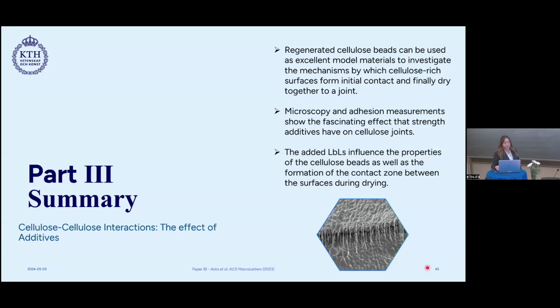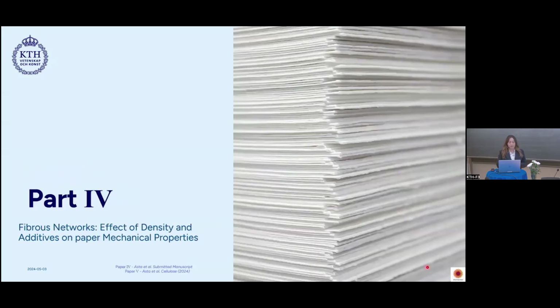So as a summary for part 3, regenerated cellulose beads can be used as excellent model materials to investigate the mechanisms by which cellulose-rich surfaces form initial contact and finally dry together to a joint. Microscopy and adhesion measurements show the fascinating effect that strength additives have on cellulose joints. The added LBLs influence the properties of the cellulose bead as well as the formation of the contact zone between the surfaces during drying. Now on to part 4, where we focus more on fibrous networks.